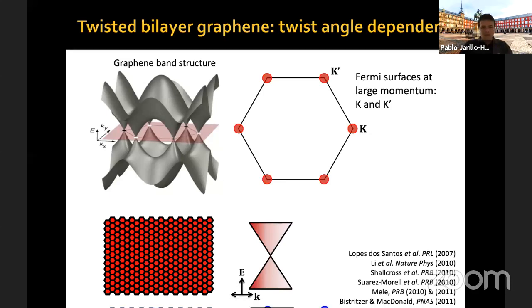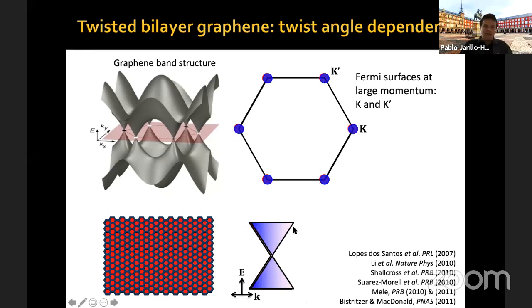If you just stack them at the exact same angle, then the electronic structures are overlapping: the real space lattice overlaps and the reciprocal space lattices overlap too. The electronic structures are just on top of each other. Now, something that you can do with 2D materials that was impossible to do before in the history of material science is that you can arbitrarily rotate two 2D materials that you stack on top of each other